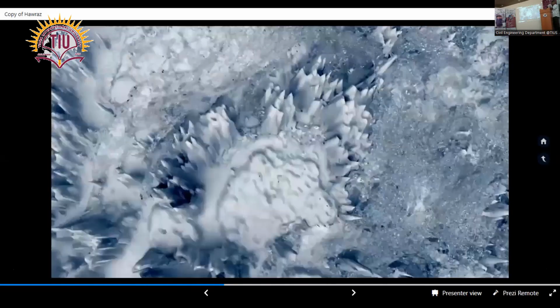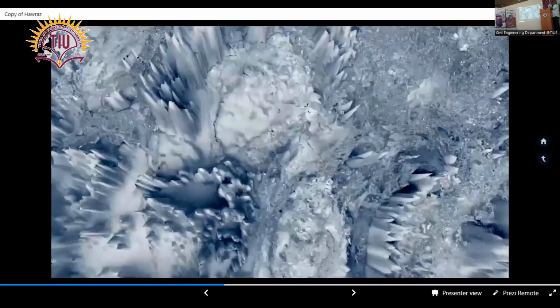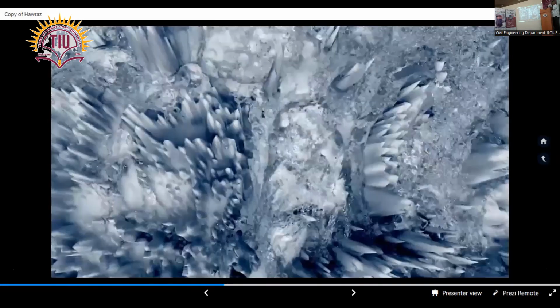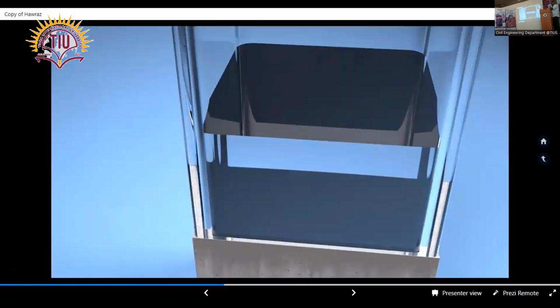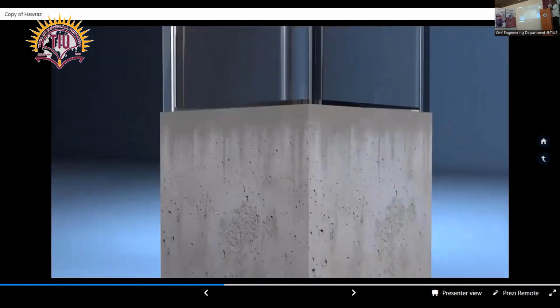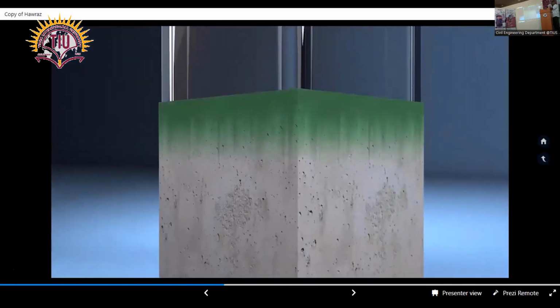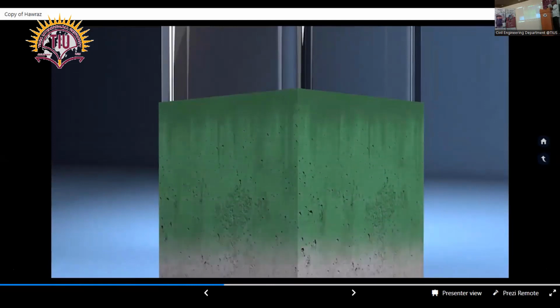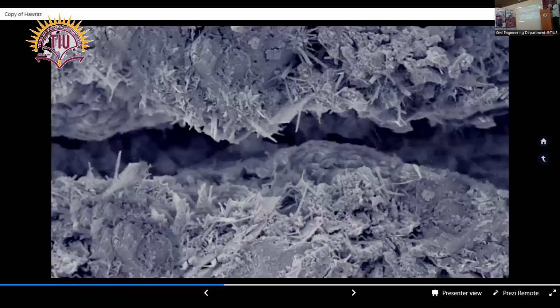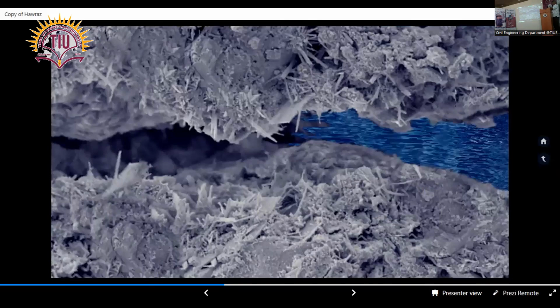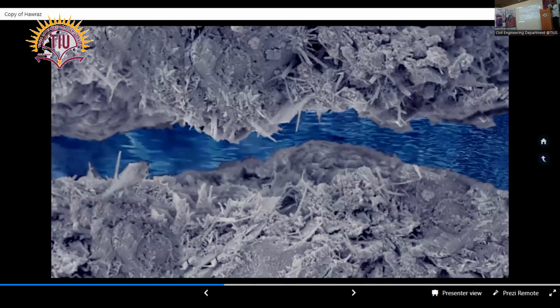Has a multitude of micro cracks, pores, and capillary tracts through which water enters the concrete. When Penetron is applied to the concrete, the structure will gradually dry out, even when facing high hydrostatic pressure. Let's take a closer look at how this works. Water passes through the capillary tracts and micro cracks in the concrete.